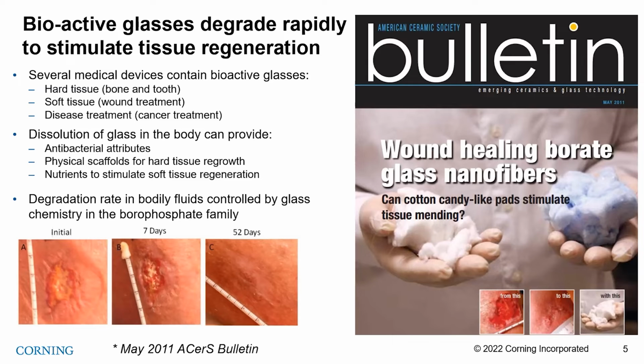And depending upon what you're trying to regenerate, you will alter the bulk glass chemistry in order to provide those right nutrients. And unlike many of the silicates that we're talking about, because of the good chemical durability attributes in those glasses, these are really focused on borate or borophosphate glasses, where they're going to degrade much more rapidly. You can see the time scale in the lower left of the order of days, right? Days and weeks that you can completely dissolve these glass materials. Next slide.